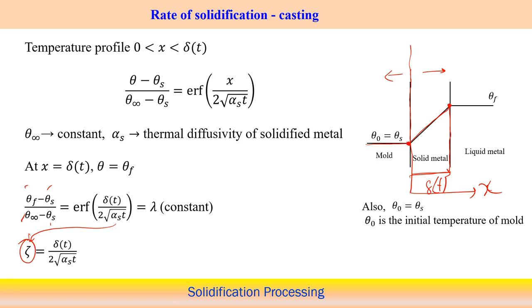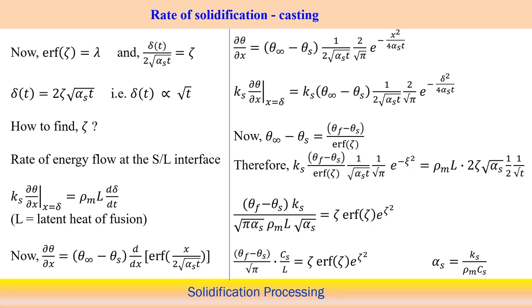Now if this is the case, before that we can say that also theta 0 equals theta s. Another boundary condition here is theta 0 equals theta s, and theta 0 is the initial temperature of the mold, and therefore no temperature gradient exists along the mold wall. So we put zeta equal to delta t by 2 root alpha t s. Now we can go further.